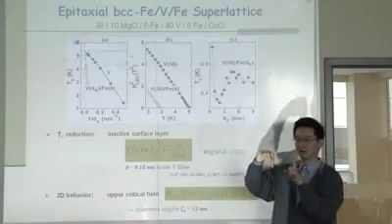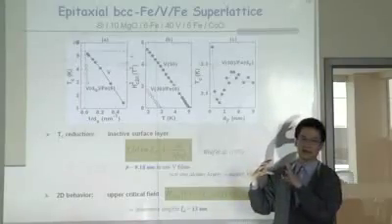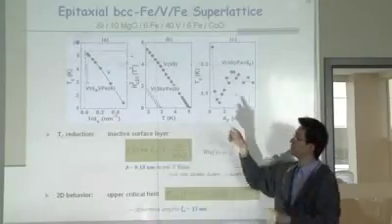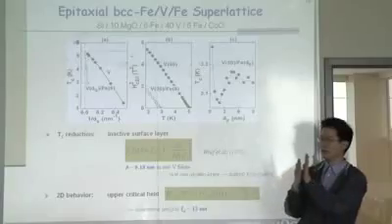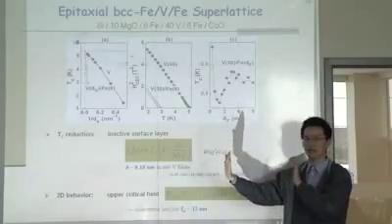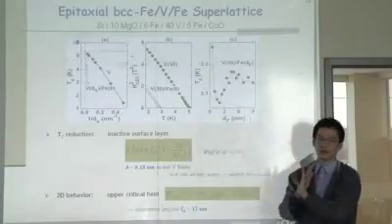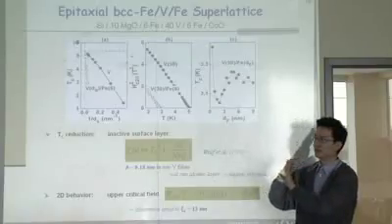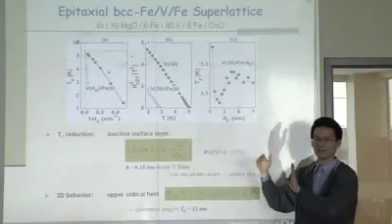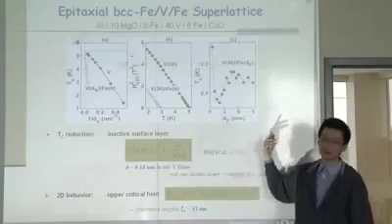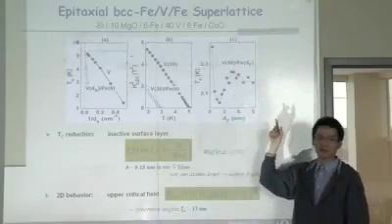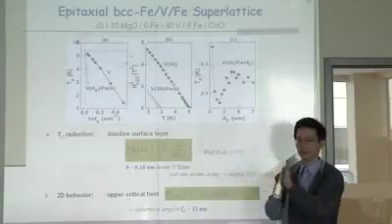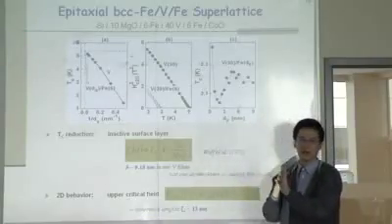As a result, the whole Cooper pair will gain a center-of-mass momentum. Then the wave function will start oscillating as a function of thickness. When the Cooper pair reaches the other boundary, it will be reflected back. And because of the oscillation in phase, the interference can be either destructive or constructive. This oscillating behavior is actually the interference between the propagating wave and the reflected wave.